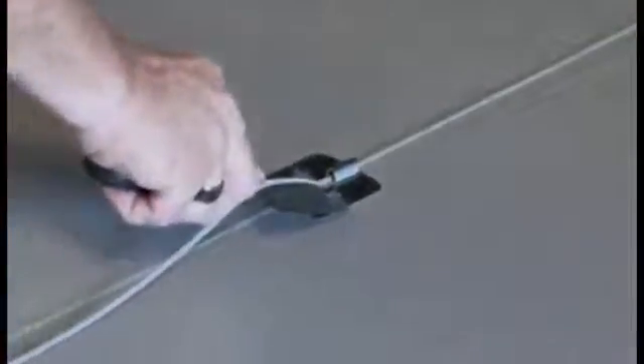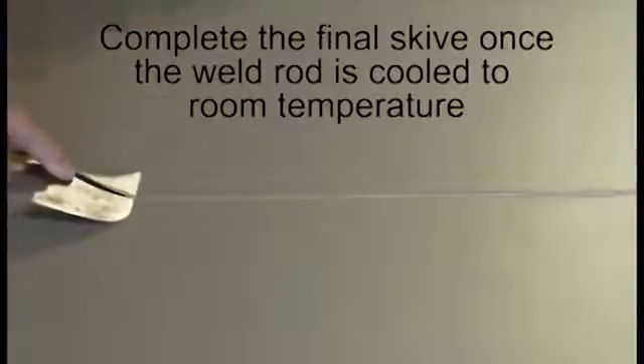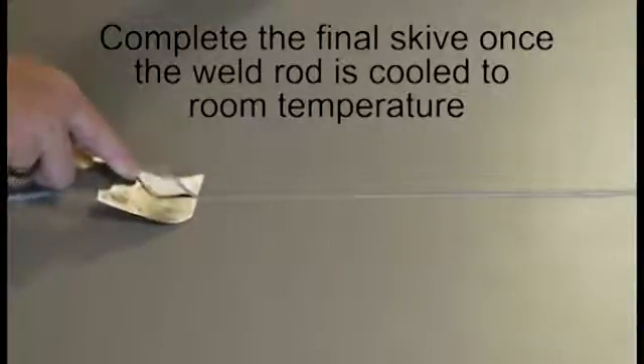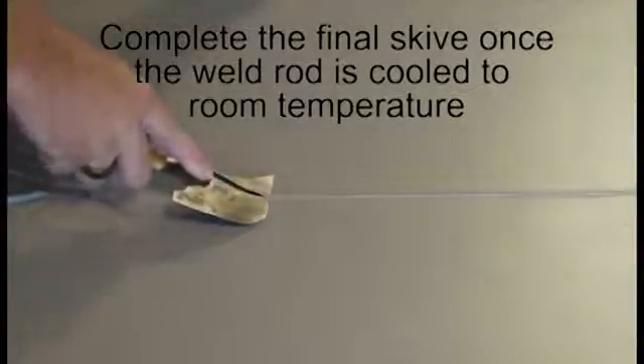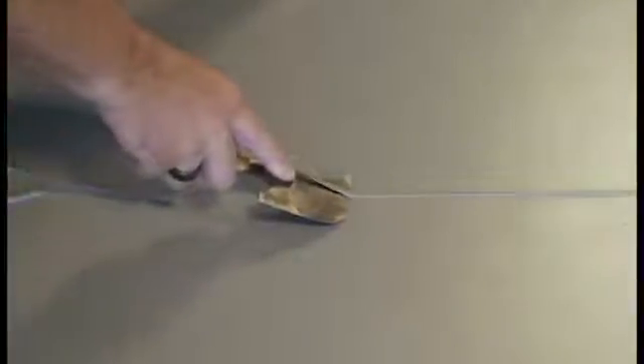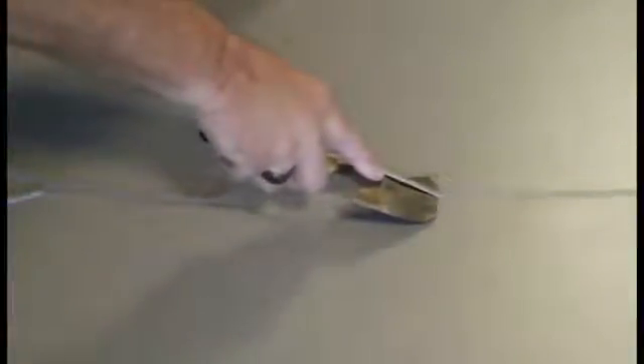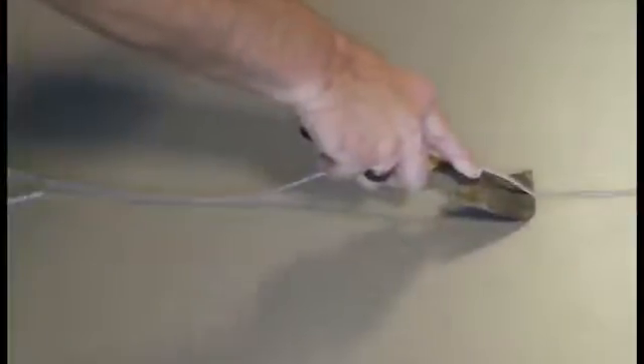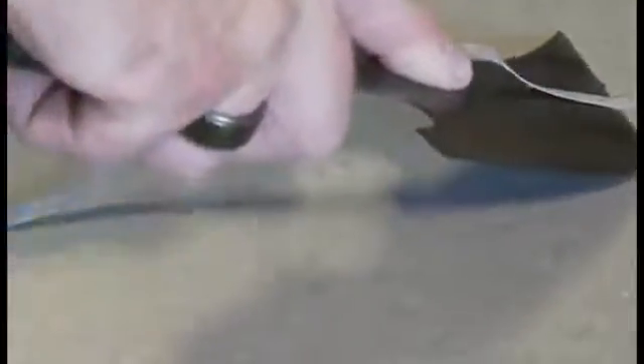Skiving the weld rod should be done in 2 passes to minimize concave seams. For the first pass, use a skiving knife and a trim plate, skiving away the top part of the weld rod while it is still warm. After the welding rod has cooled to room temperature, skive the remaining weld rod on the second pass by holding the skiving knife flush with the floor. Smooth, continuous passes result in a smooth seam. Repeated start and stop action results in rough seams. After the final skive, wipe the seam with a clean, damp cloth.